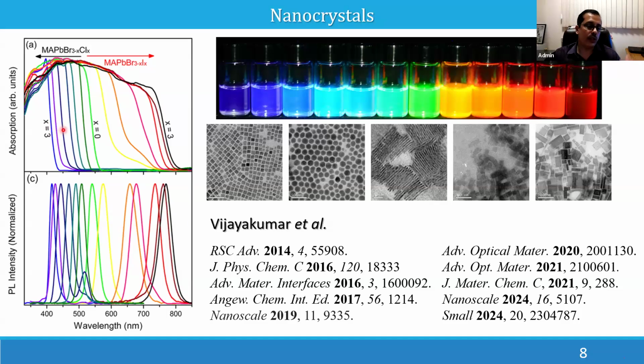Again, you reduce the number of chlorides and move to more and more bromide. If it is all bromide, methyl ammonium bromide, Br3, then you will get a beautiful green color like this. And then you further move to the iodide part. In that case, you are replacing the bromide with iodide. Then it will start moving to yellowish, then to orange, red and deep red. In the all-iodide case, you will get an NIR spectrum. Here you can see it is above 700 nanometers, coming close to 800 nanometers.